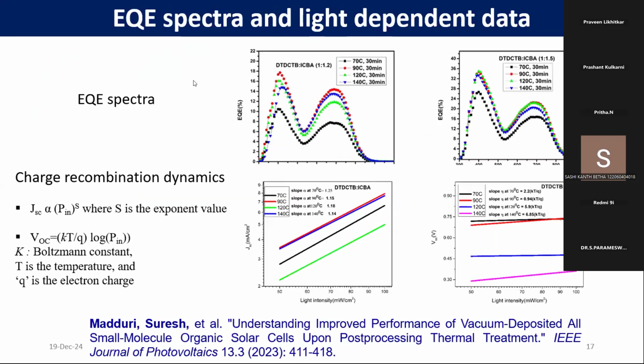And then we also need to calculate the external quantum efficiency. External quantum efficiency is nothing but the number of charges collected per incident photon. So in the case of DT-DC-TB and ICBA at 1:1.5 at 90 degrees Celsius, 30 minutes annealing temperature, it was giving around 35% external quantum efficiency. So this is how we can calculate the external quantum efficiency, and if we integrate the external quantum efficiency with the unit charge, we can obtain the current density JSC.